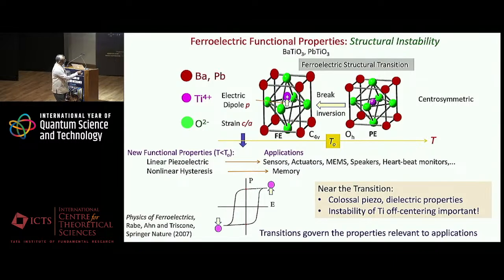And once you break this inversion symmetry, new properties emerge, like linear piezoelectric response and nonlinear hysteresis, as shown here, polarization versus electric field. And these emergent properties are only in the low temperature phase, which makes it useful in sensors, actuators, speakers, and microphones in your mobile phones, and a variety of applications from heartbeat monitors to naval submarines. Yeah? So near the phase transition, these response properties are colossal in magnitude, and the instability of titanium off-centering is very important to these transitions.